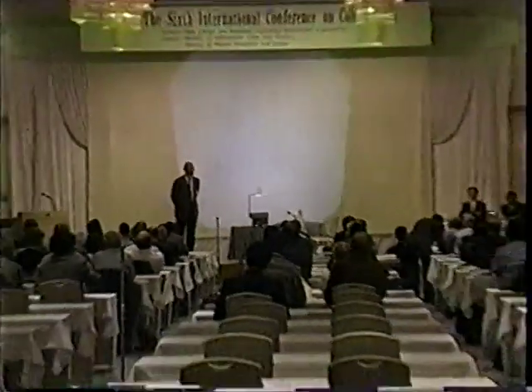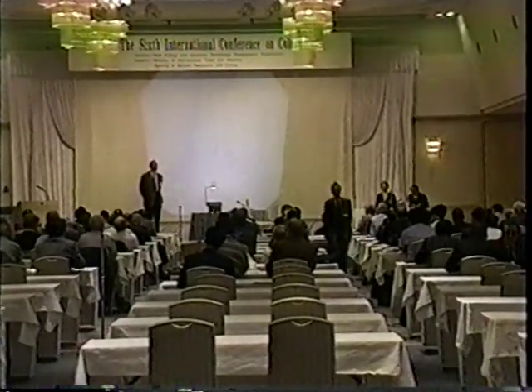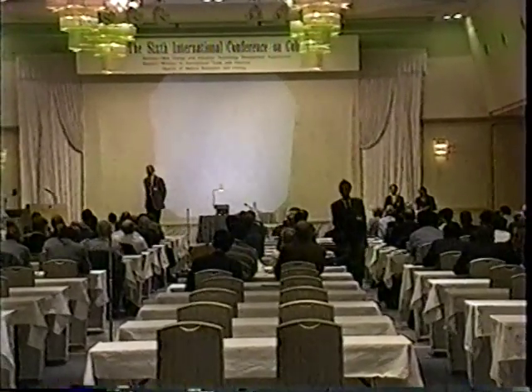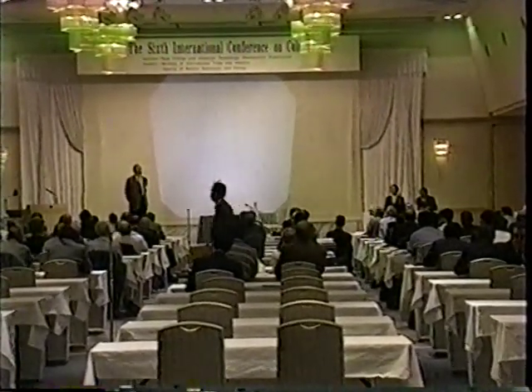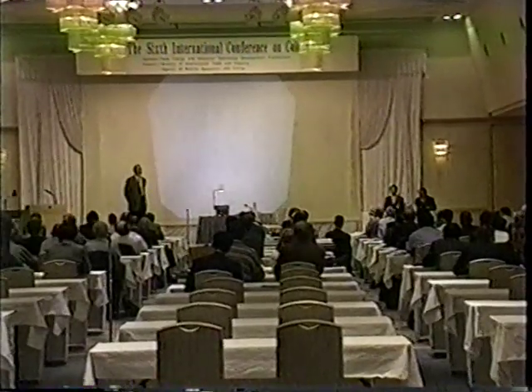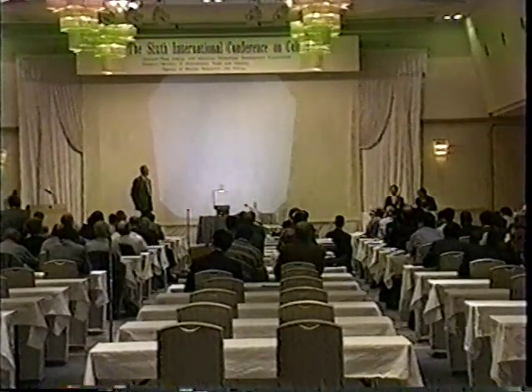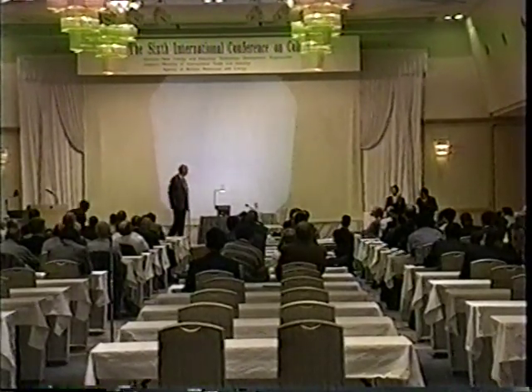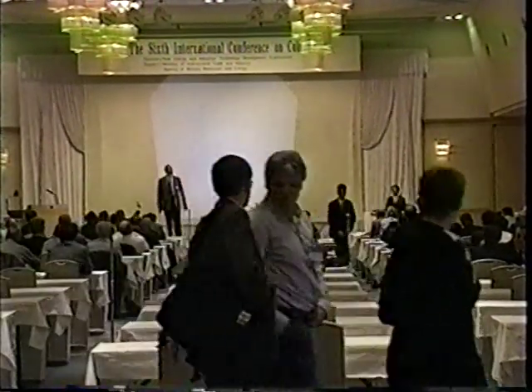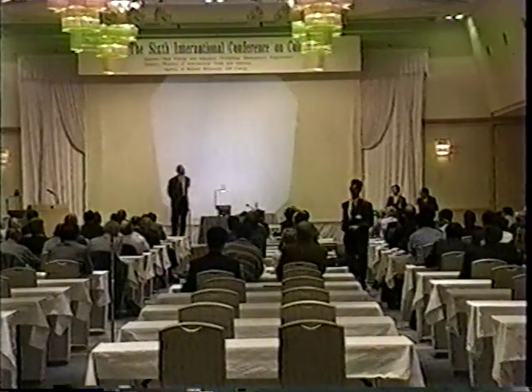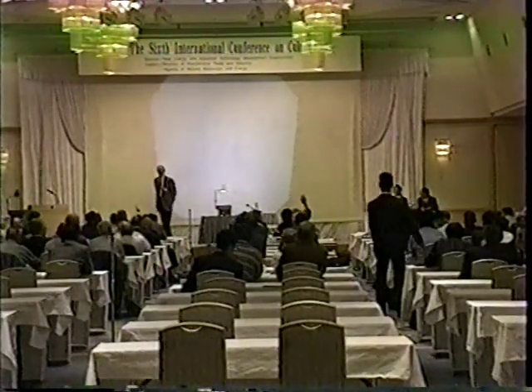So this result is in contradiction with what we had the previous 3 days, which said you must have 0.8, 0.9, 0.99. It's clear that the conditions required for heat production and the conditions required for tritium production are somewhat different. It's not the same nuclear reaction. It's apparently not even the same environment within the piece, and it is subject to different pressure effects. That's a very big conclusion. Well, it is a conclusion that is clearly derivable from the observation, if you believe the observation. I mean, that's the hope.